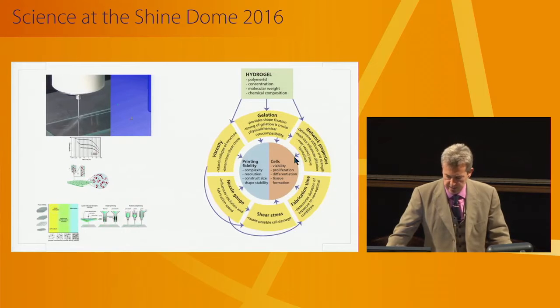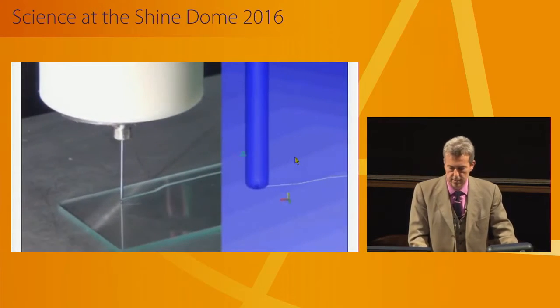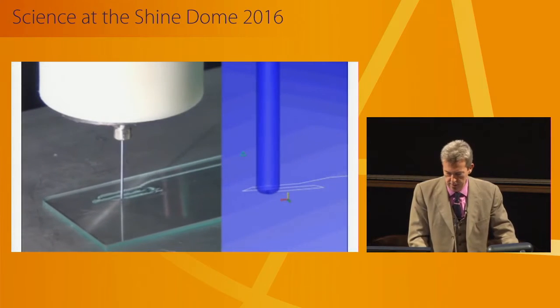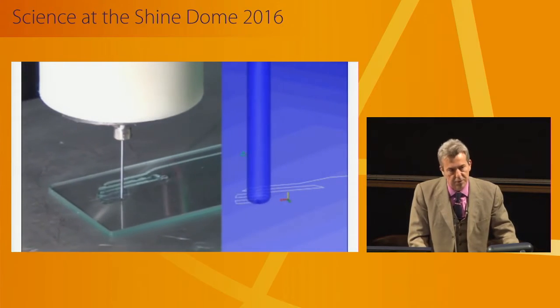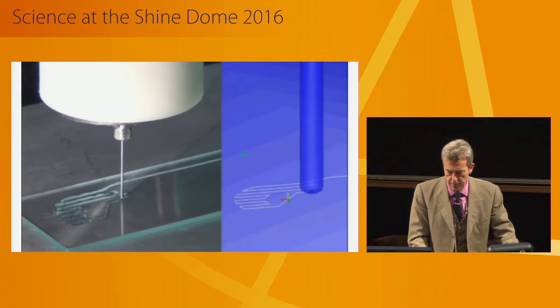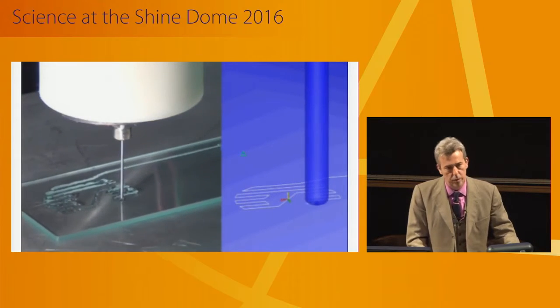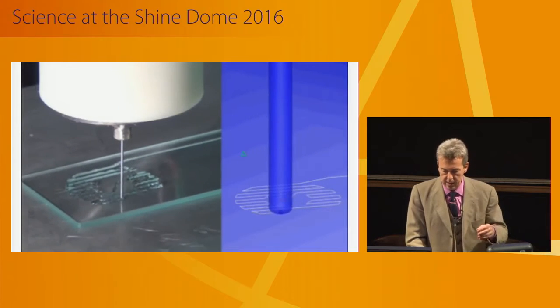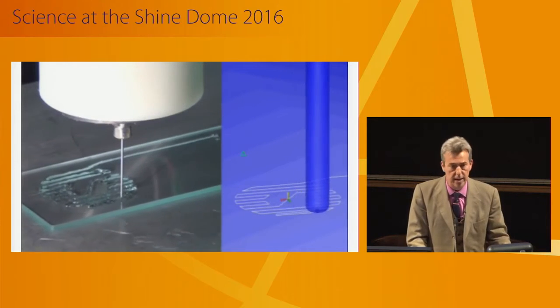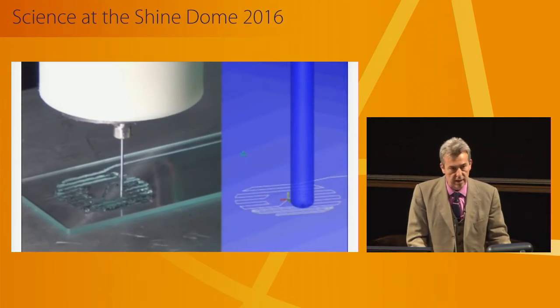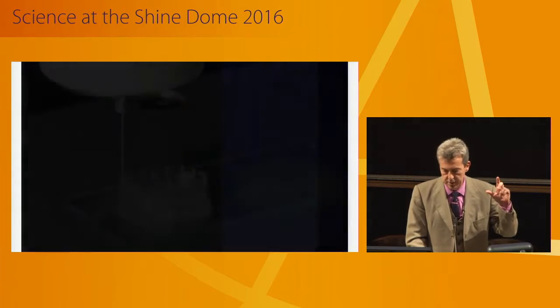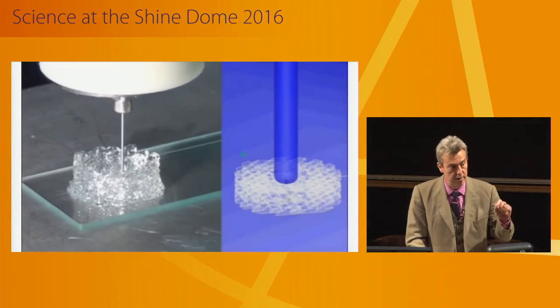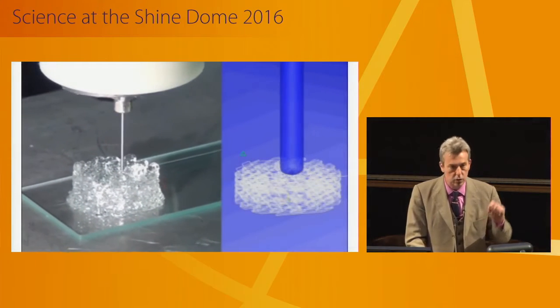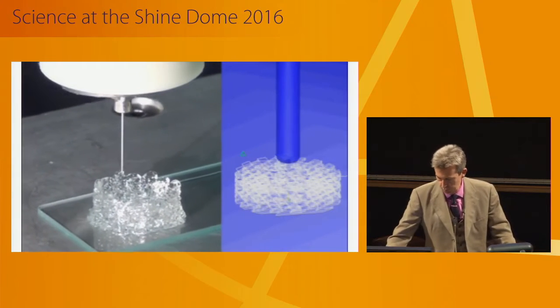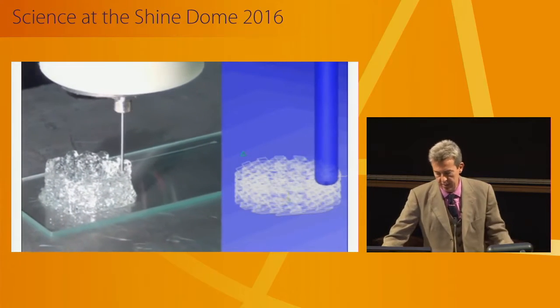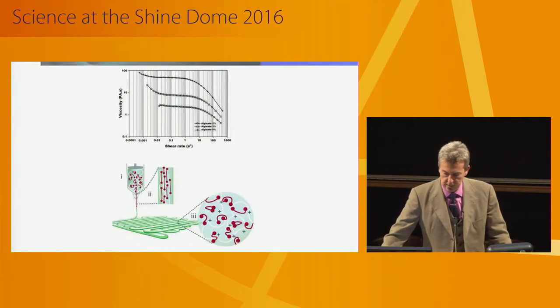So this leads us to the complexity. So here you see us printing cells in a hydrogel. But some of the issues is that, and I get to this in a moment, that we need to develop these biomaterials which are highly cell compatible, but which allow us not just to print the strands in one layer, but really to build this up and get to dimensions in the Z direction, which are 1 centimeter, 2 centimeters, 3 centimeters. And this is a big challenge for us to do this also with a very high spatial resolution, because that is needed because we want to direct the cells to form the tissue which we desire to do.